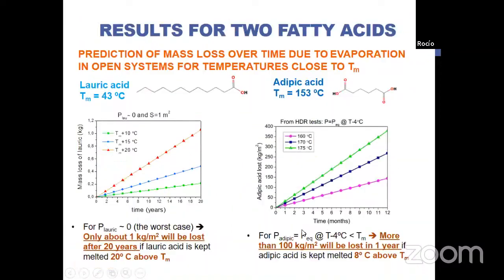Okay. So just to show you, before finishing, some results that we obtained for two different kinds of fatty acids that are normally considered as phase change materials. In the end, what we want to do with all these studies is to predict the mass loss over time due to evaporation, because these acids undergo evaporation when they are in open systems. Of course, what is interesting for us is to see what happens at temperatures close to the melting temperature, not very far, but close.